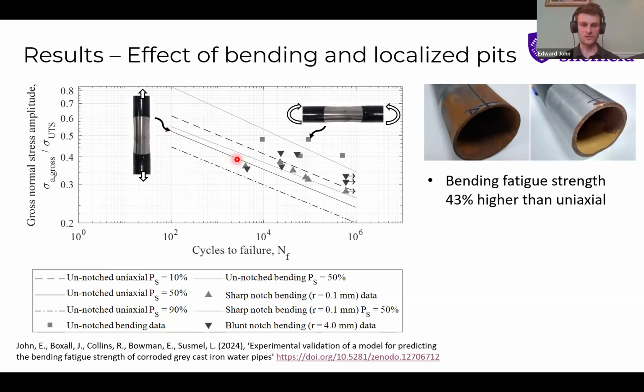So the first line to look at here on this rather busy graph is this solid black line. This is our reference curve. This is if you just stretch and compress a piece of cast iron, so tensile loading. That's basically the curve that you get. So what we looked at was what happens if we use bending loading instead of this standard uniaxial loading. And so this is this grey line up here and these grey squares. And actually the interesting thing here is that the bending fatigue strength is 43% higher than the uniaxial strength. So actually bending loading represents a less damaging case. So if you have a pipe that's mainly experiencing bending loading, it's probably less bad than uniaxial loading, or indeed pressure loading, because those two are quite similar.